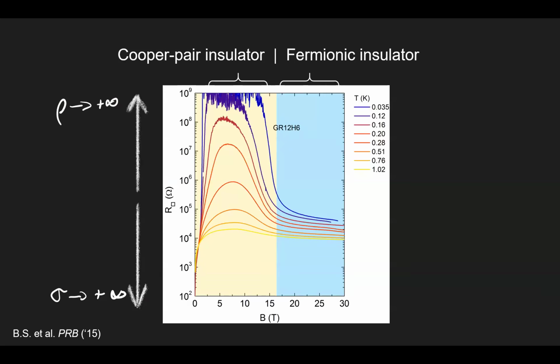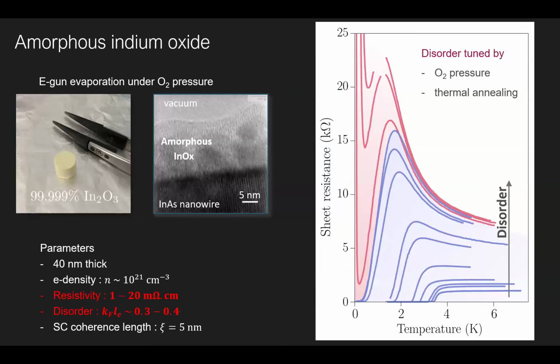Okay, all right. You may wonder what is the material that gives all these characteristics. This material is amorphous indium oxide. This is a very well-known material in the field and actually in society, because if you put a little bit of tin in this material, you get the famous ITO that you all have in your touch screen, which is this transparent conductive electrode. And if you keep only indium and oxygen, you get an amorphous material which undergoes a metal-insulator transition and also a superconducting-to-insulating transition that is captured here with this series of films where you see the Tc decrease as a function of the resistance.